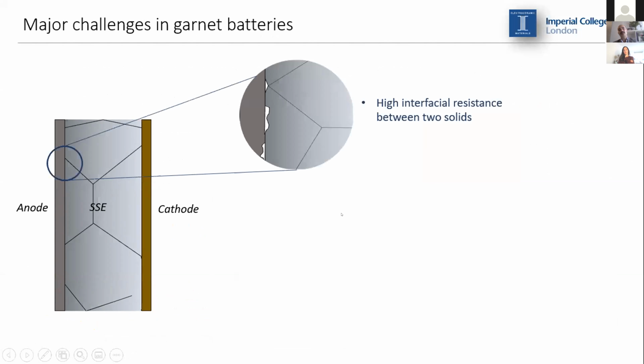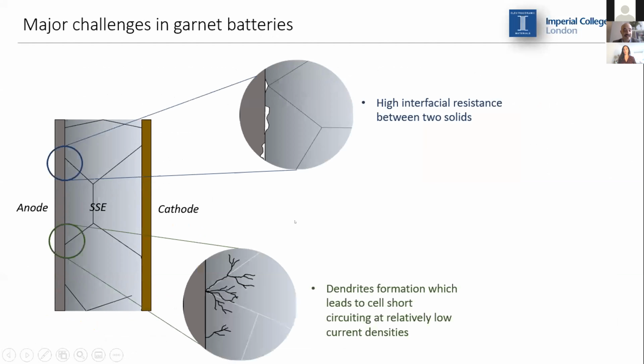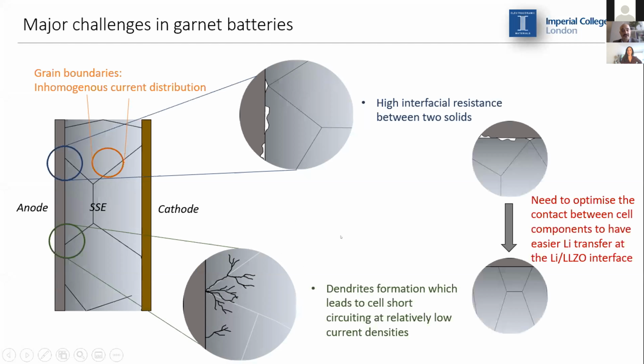So as Ainara said, the contact in between two solids can lead to high interfacial resistances if the contact is not perfect, so if we have voids at the interface. And if we have voids, we've got points of contact in which the current density upon cycling will be very high. And this could lead to the nucleation of lithium dendrites and their propagation through the solid electrolyte. And we will see that even the composition of the grain boundaries can play an important role in the propagation of dendrites through the electrolyte.